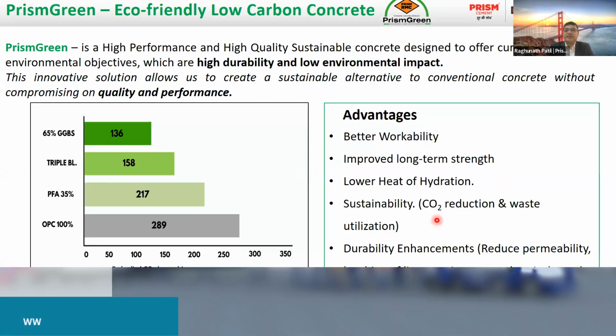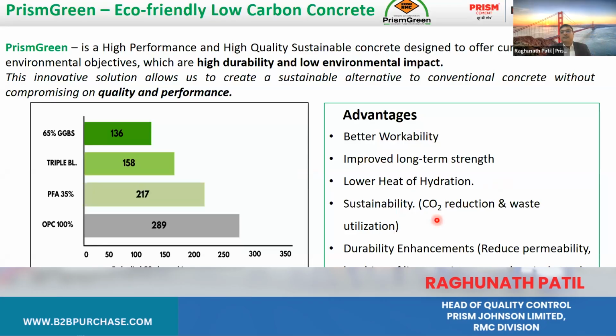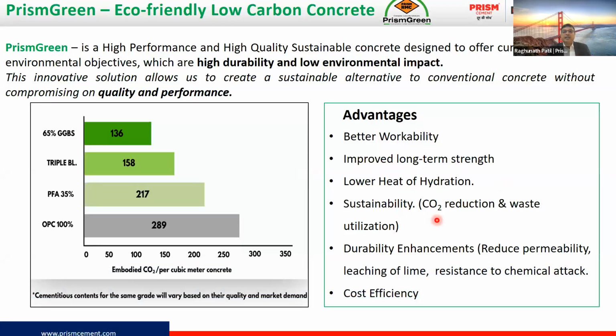Sustainability is CO2 reduction, because we are reducing the cement content. The CO2 from the manufacture of cement is very high. Globally it is around 8% of total global CO2 emissions, while producing the clinker. So if we reduce the cement content by 35 or 50%, then we can directly reduce the CO2. And waste utilization, since fly ash and GGBS are industrial waste which are actually very challenging to dispose of. That's why we are using them in this concrete, and it is very useful.